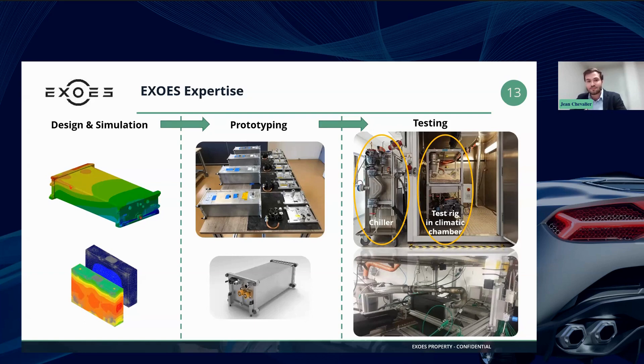The specific test performed to assess the safety of the prototype is called an abuse test. An abuse test consists in artificially triggering a thermal runaway inside a battery module in order to monitor the phenomenon and assess if and how it propagates to the other cells of the module, which is usually the cause of battery fires.